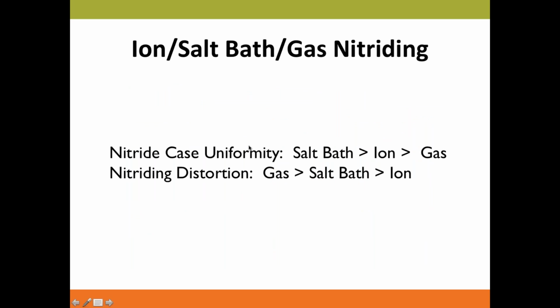So just due to the nature of the process, the nitride case uniformity means, let's say I want 10 thou, I'll always get 10 thou bang on across all dimensions. Salt bath is the better one because when you put it into the bath, the temperature of the sleeve is very uniform, and nitride is a temperature activated process. You have a uniform temperature, so the case depth is very uniform. So salt bath is better than ion and better than gas. It's just because for the gas you need to operate at a higher temperature. There's a higher danger of temperature distribution problems, and the gas is generally a less preferred conductor for the heat.